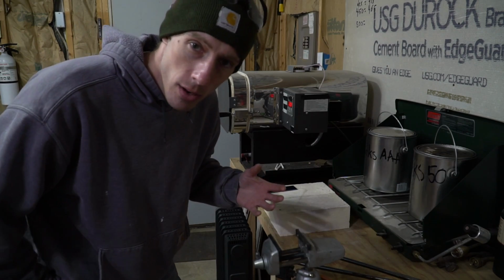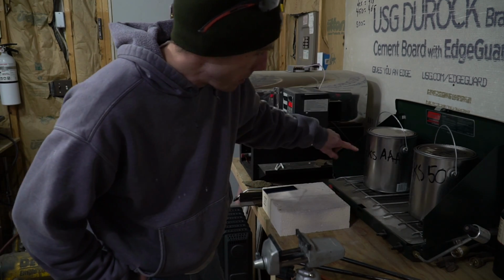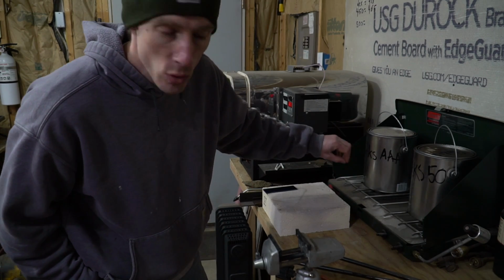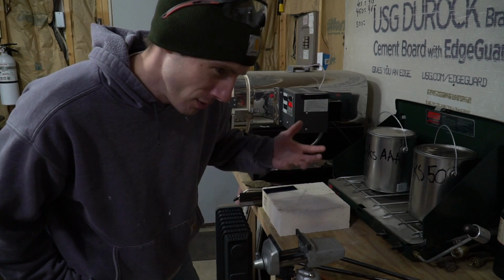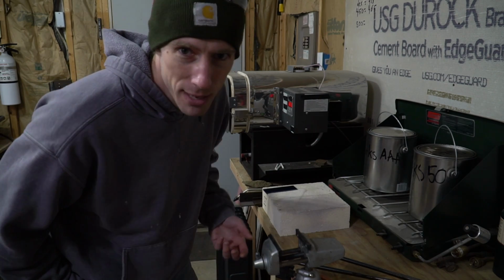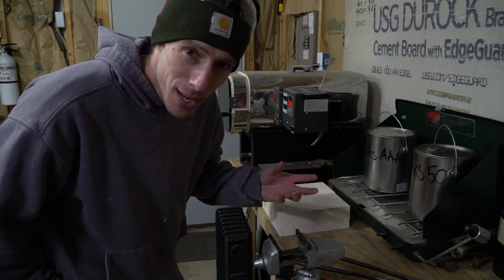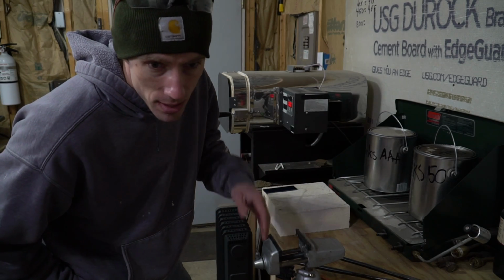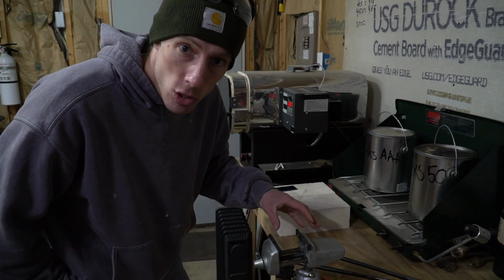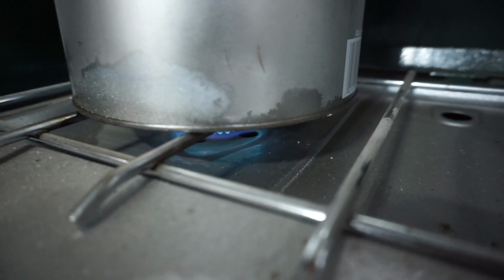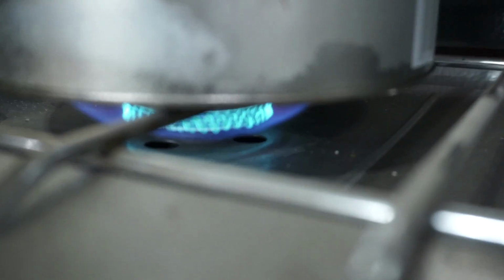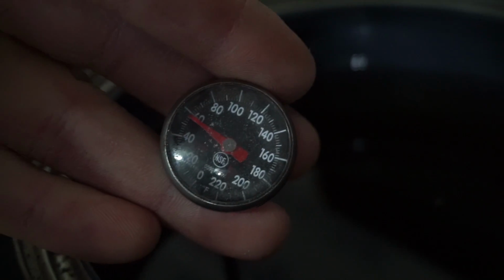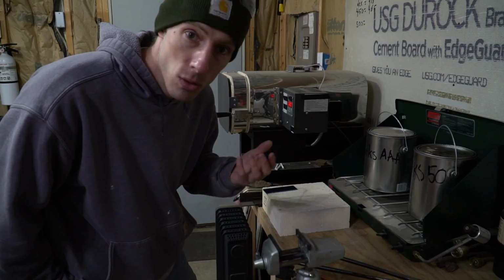Okay, so while that's cooling down, I'm going to go ahead and get our oil ready. I'm going to be using Parks AAA as our quench oil. I'm going to preheat it to around 100 to 120 degrees or so. And I preheat it simply because it gives me consistency. Right now it's 40 degrees in the shop. If I'm in here during the summertime, my quench oil is going to be much warmer than 40 degrees. So I just go ahead and preheat it to 100 to 120.